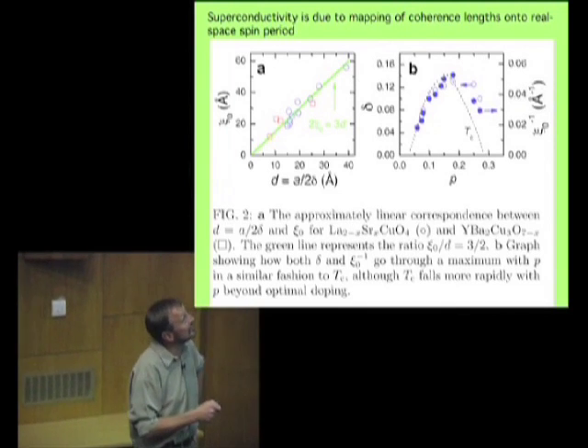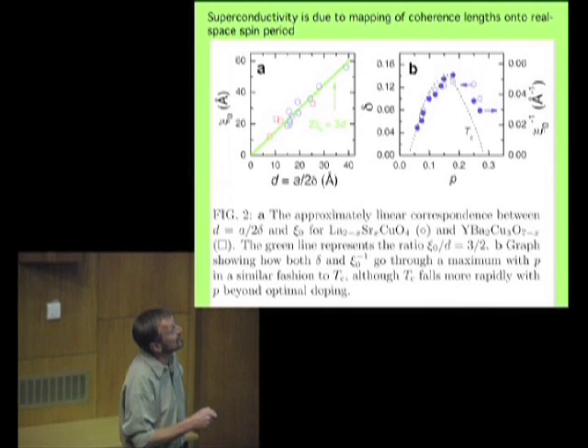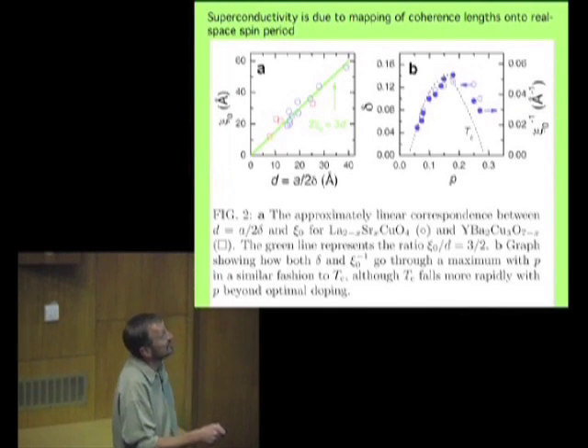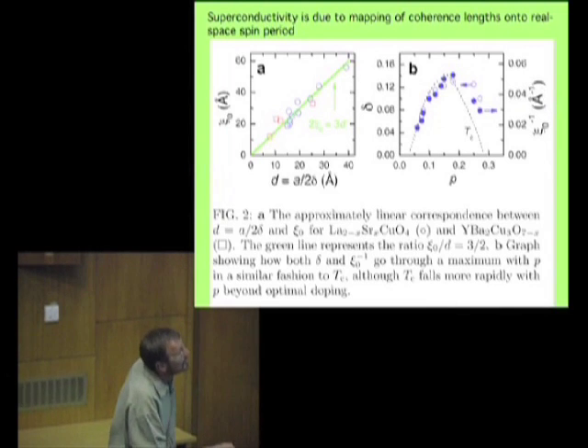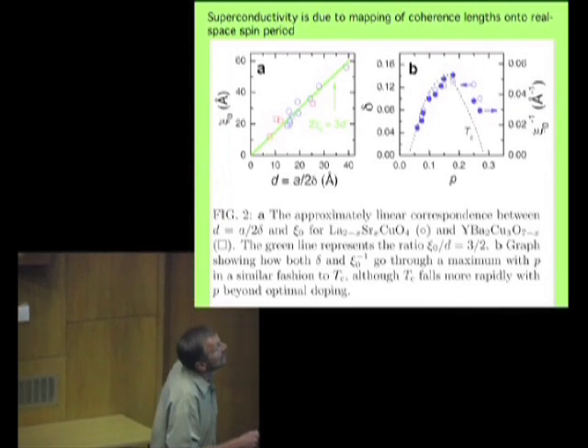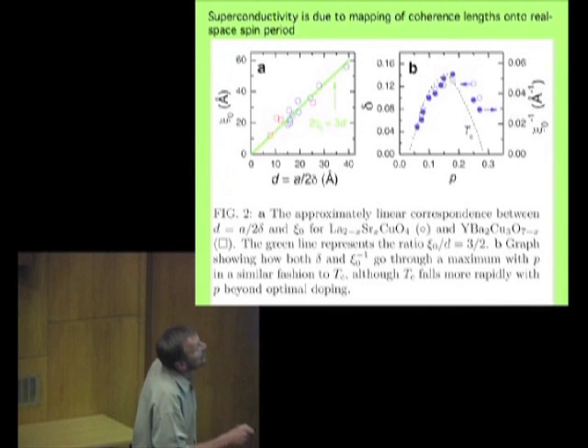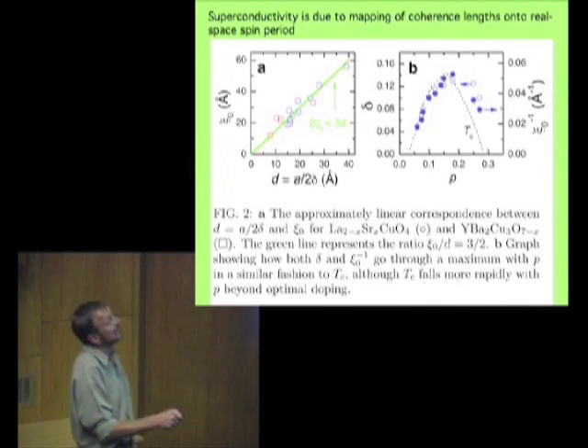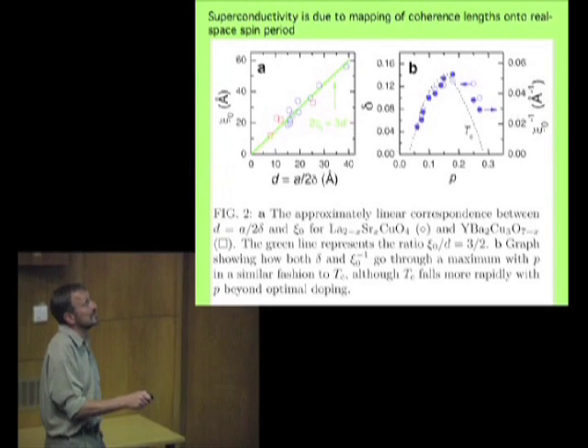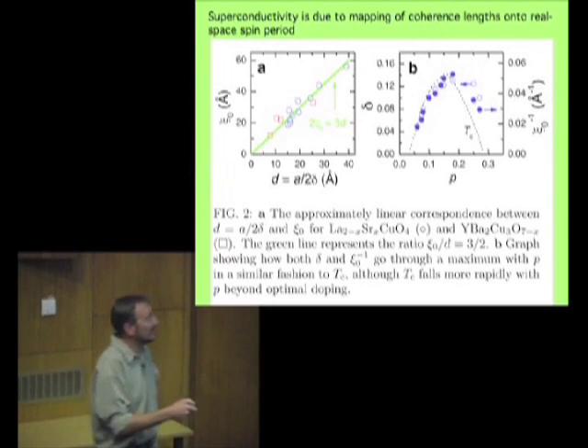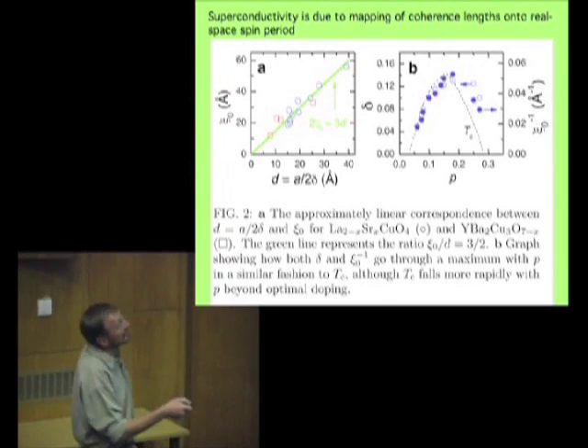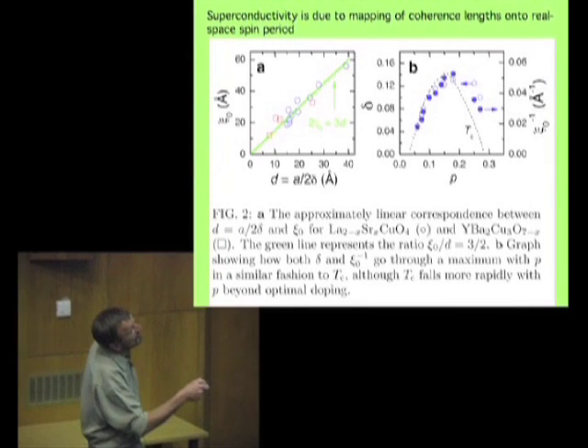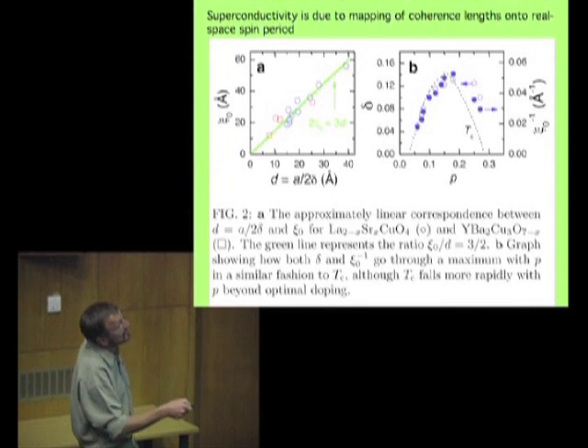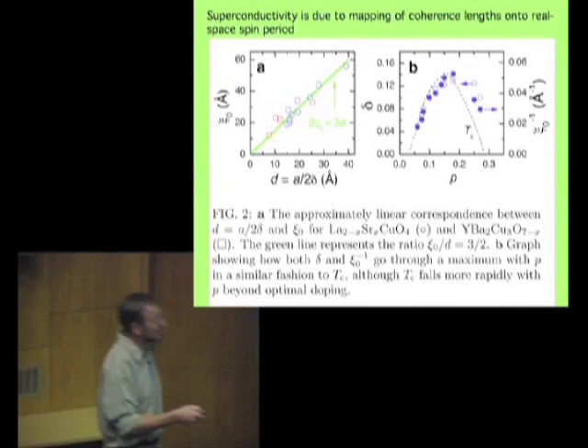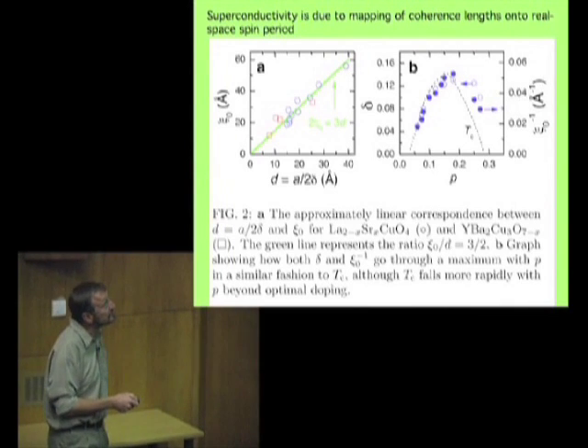You can even look at the plot of delta, the parameter which determines the inverse of the coherence length, and the coherence length to the -1. Remember, this is a theoretical link between the two, and they follow the same sort of behavior, skewed a little bit, as the superconducting transition temperature does. So obviously, I think, these antiferromagnetic fluctuations, which are caused by the spin susceptibility, are very closely related to the superconductivity.